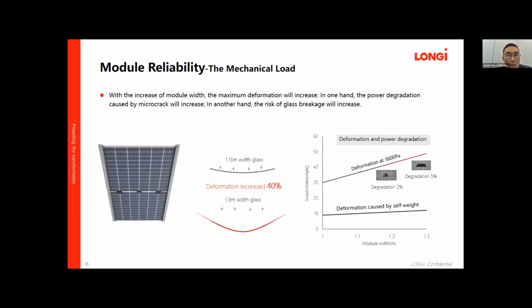And also for the mechanical loading, we did analysis on different module widths. With the increase of the module width, the maximum deformation will increase from 1.13 meters to 1.3 meters. The deformation will increase about 40%. So on one hand, the large deformation will cause about 3% higher power degradation, and on the other hand, the risk of glass breakage will increase.